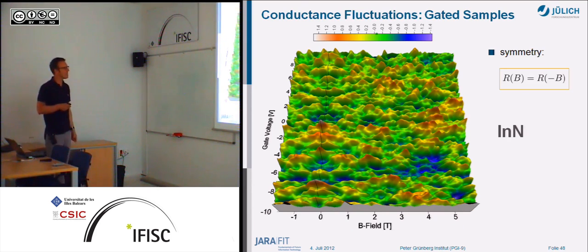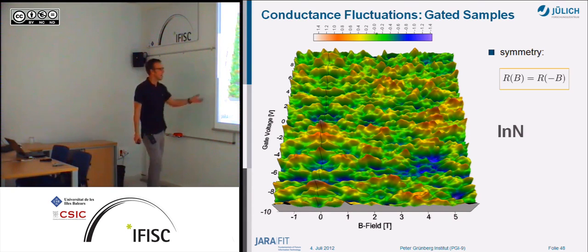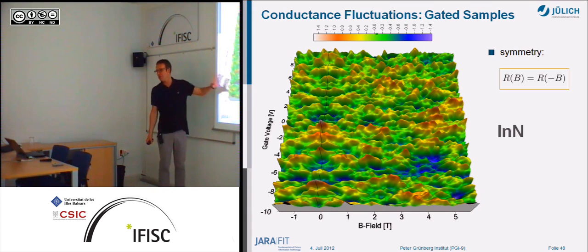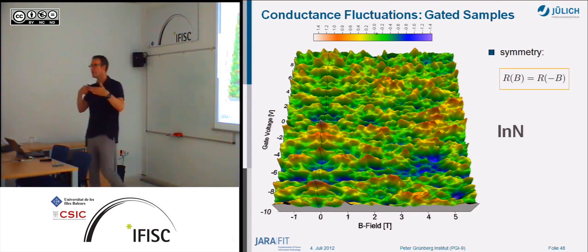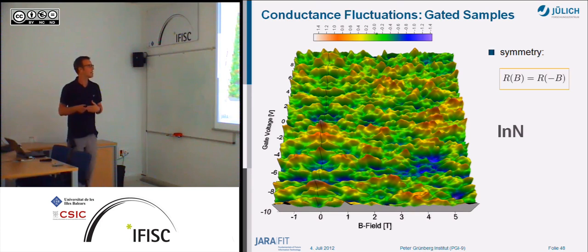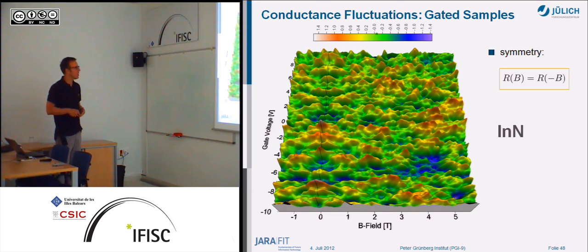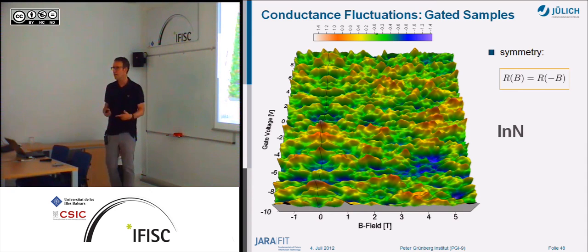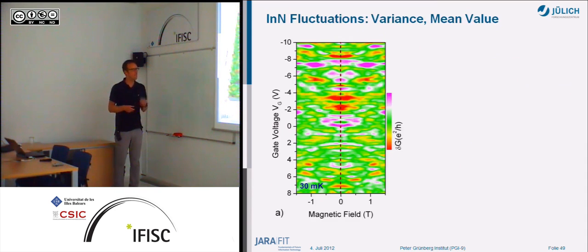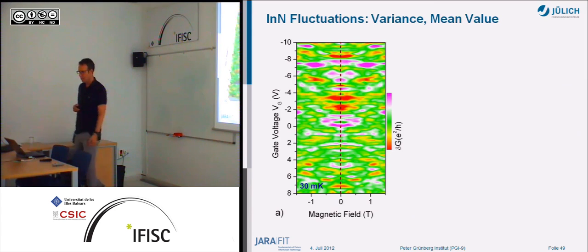The reason is that you have some bad thing you have to consider as well. As I showed before, because you have such a small structure, you have universal conductance fluctuations. And this effect is quite strong and masks all this localization effect. Yeah? And so what you have to do is not only measure the conductance as a function of magnetic field, where you get all these fluctuations, but you have to change the gate voltage as well in order to do some averaging at the end to get then some information about the spin-orbit coupling.